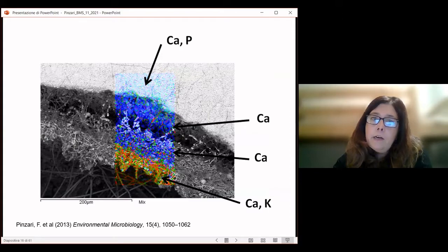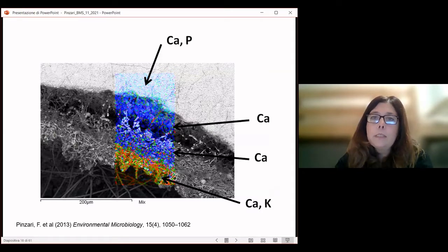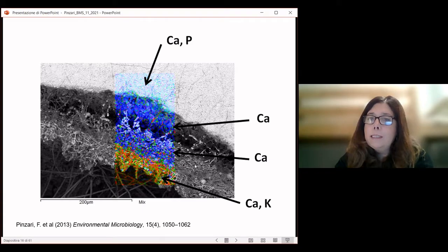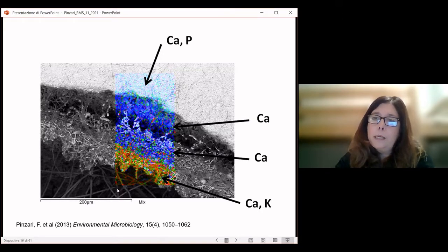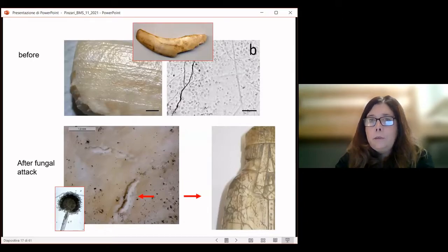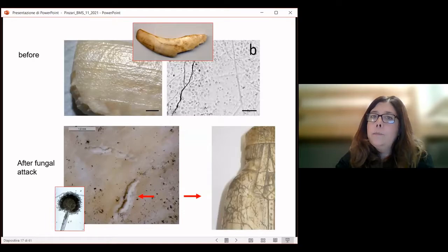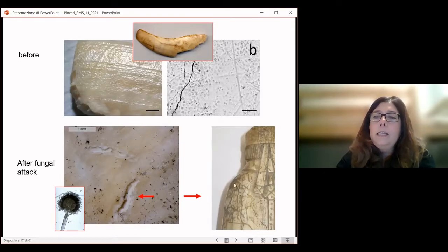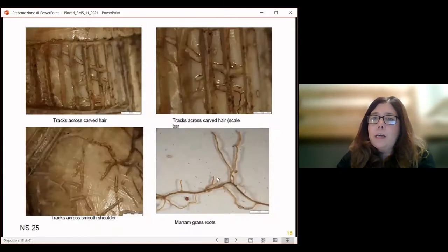In cross-section under the optical microscope, there is a clear layer of secondary minerals. These are the conidiophores with conidia of Aspergillus, and this is the pristine ivory. Under the scanning electron microscope you can see the apatite, a layer of secondary minerals — mainly calcium oxalates — the mycelium with hyphae covered with calcite, and other minerals concentrated in the mycelium like potassium. Removing the mycelium from the surface, the pristine appearance of the tusk revealed tracks deep and large enough to be compared with the tracks found on the chessmen.